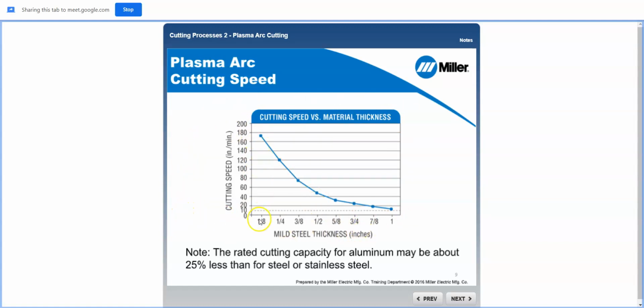As you can see, as our material gets thicker, our cutting speed decreases. So for a machine that is rated for 1 inch thick material, it can cut 1/8 inch material at about 170 inches per minute, which is pretty dang quick. But as we go down the line, you can see how we just steadily decrease until we hit the machine's maximum capacity, which is looking about 12 inches per minute for 1 inch thick material. So we go from 170 for 1/8 inch all the way down to 12 inches per minute for 1 inch thick material.